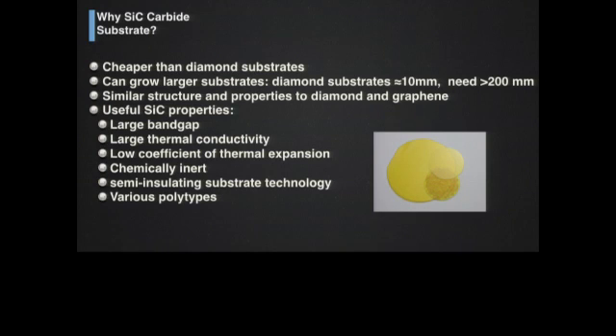Silicon carbide has a structure similar to some of the properties of diamond and graphene, and so there might be some synergy of not only taking advantage of growing diamond on top of silicon carbide, but you might also get graphene as another byproduct of that substrate technology. So the useful silicon carbide properties would include large band gap, large thermal conductivity, low coefficient of thermal expansion, and it is chemically inert. And this is a real big advantage if you want to think about diamond as somewhat of an electronic device: the fact that you can get silicon carbide semi-insulating substrates. So that's really a big issue. And it's one of the main reasons why people have done sublimation of graphene on silicon carbide, because now they have a semi-insulating substrate technology.